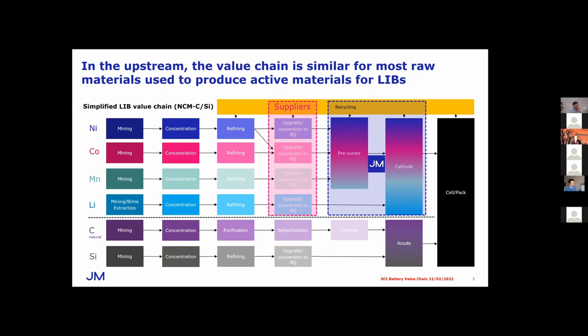And then conventionally, there would be a conversion or upgrade to the battery quality standards that the industry requires, then to blend or manufacture into the actual active materials themselves. Where Johnson Matthey was playing was in this precursor and cathode step of the value chain, taking mainly nickel and cobalt and lithium in salt form, converting that to a precursor initially, and then producing the cathode materials via calcination and lithiation, that we then supply to the lithium-ion battery cell manufacturers for onward use through to various applications, but in particular the automotive industry.